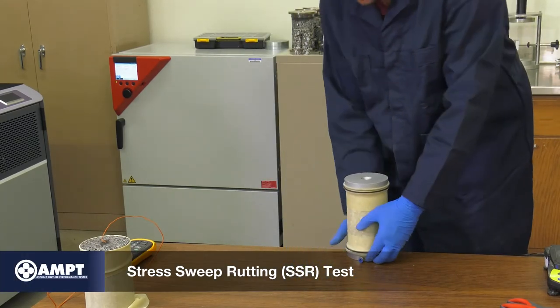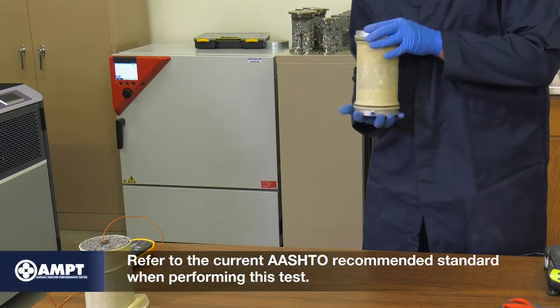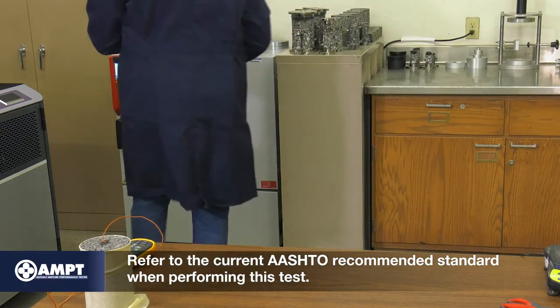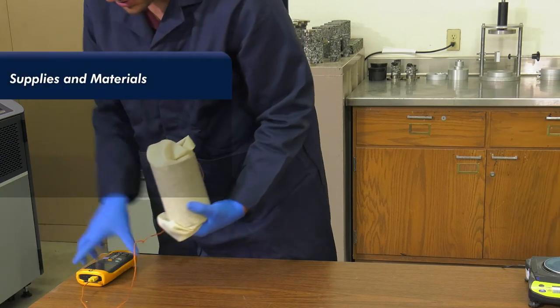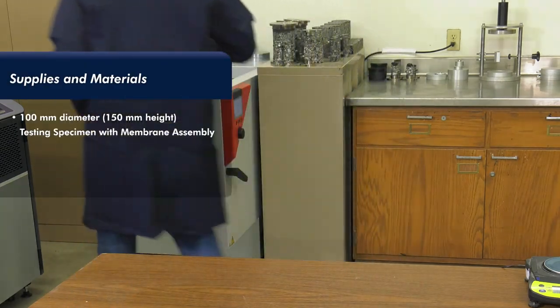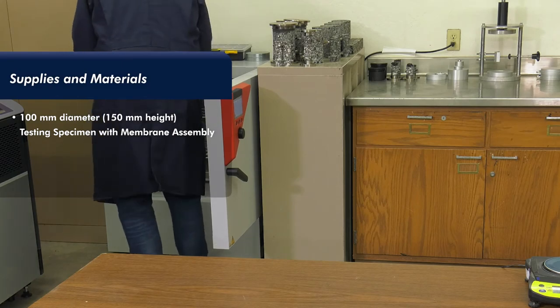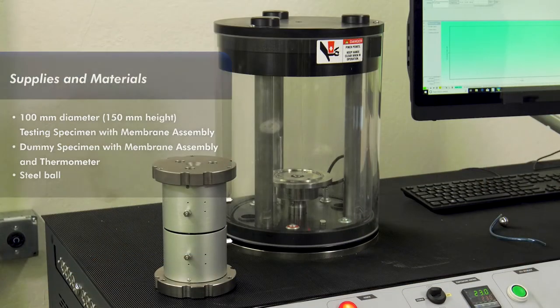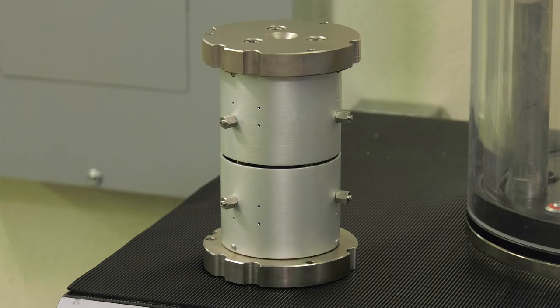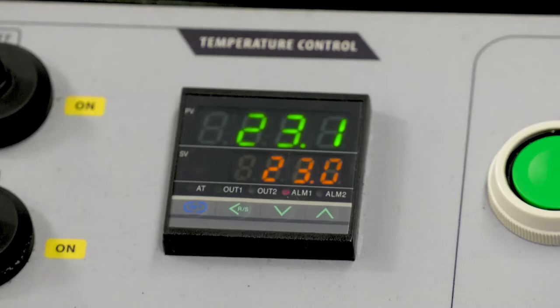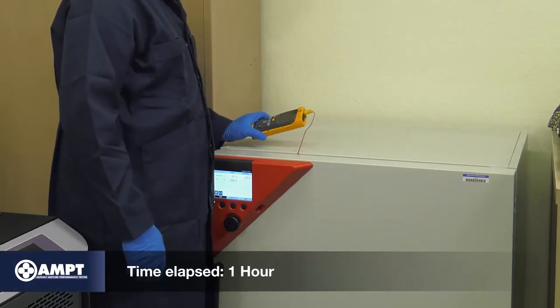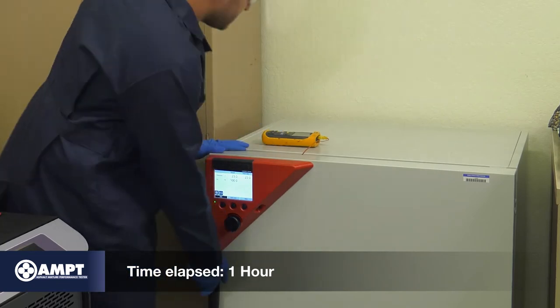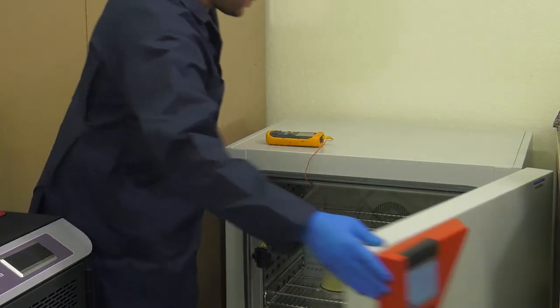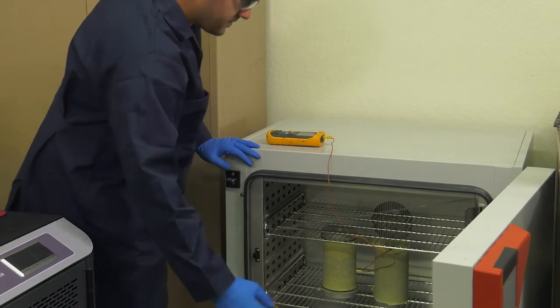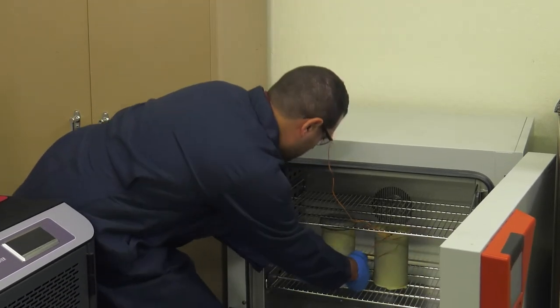Refer to the current AASHTO recommended standard when performing this test. Place both the testing and dummy specimens in the external environmental chamber until the dummy specimen reaches the test temperature. Refer to the recommended test temperatures given in the standard. Verify the calibration of the AMPT using a proving ring before beginning this test. Turn on the AMPT and set the temperature control to the desired test temperature and allow the AMPT conditioning chamber to equilibrate for at least 1 hour. Once the chamber is conditioned and the dummy specimen has reached the target temperature, start setting up the test specimen in the AMPT conditioning chamber.